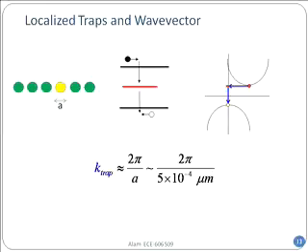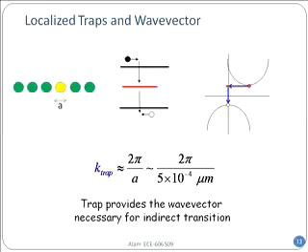You can immediately see physically why indirect band gap recombination is so difficult. The electron needs to be first captured by a trap. If you don't have a trap, it's not going to recombine at all. Once it has a trap, then it has to wait for a hole to come along. So this recombination is on the order of a millisecond to a microsecond. How would you shorten it? Just increase the number of traps. We'll see with a transistor or a diode how this increase actually helps the performance of a diode later on.